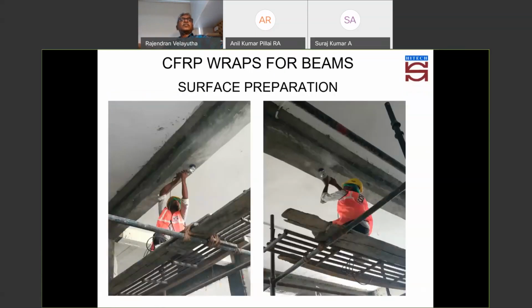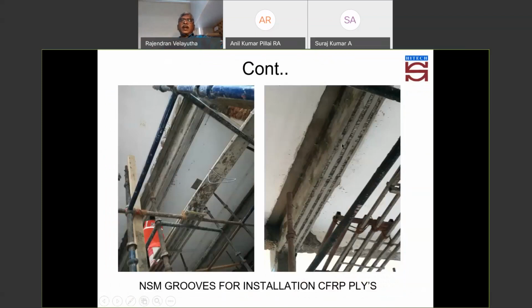In this case, this has been done with a normal plaster. And now coming to the beam for the CFRP, we had an issue of cover thickness. Although we are supposed to have a 20 mm cover thickness, we had only a maximum of about 15 mm, and there are places where we have only 8 mm.